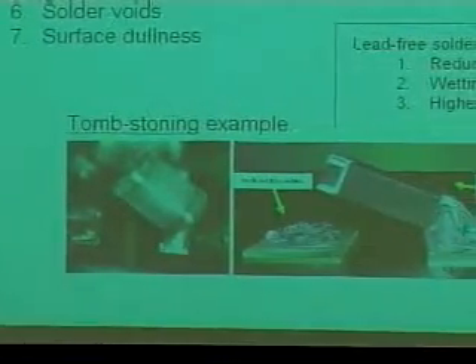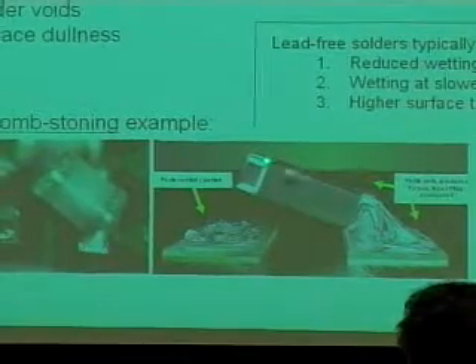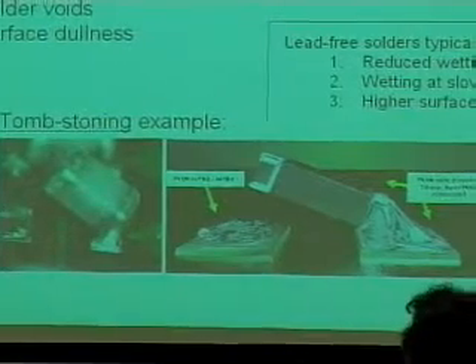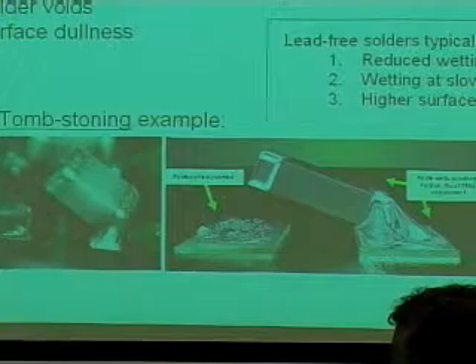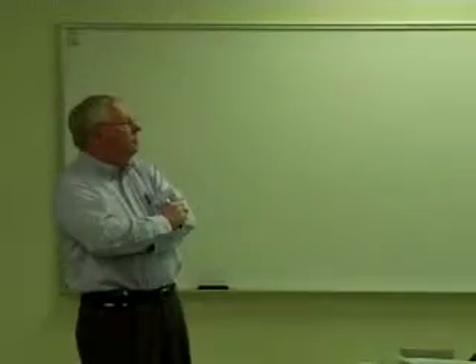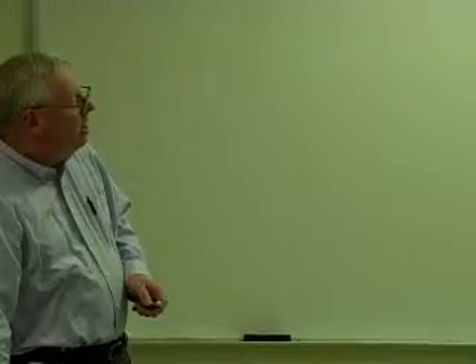Okay, there are other defects that can occur. This is something called tombstoning, which I think is very interesting. Pretty obvious this is a defect, this is a flaw. And what happened is, you can see, this probably turned to liquid sooner. The surface tension is favorable, and it actually lifted this very light component. So you can see, in lead tin, you can also see some tombstoning. It's not just lead-free solders, but it's probably a little more prevalent in lead-free solders than in tin-lead solder. So tombstoning can be a problem. If it doesn't get sufficiently hot, you'll get cold joints. And I think we all know what cold joints are in soldering. Not good. Voids, voiding can occur in solders, and that is not good.